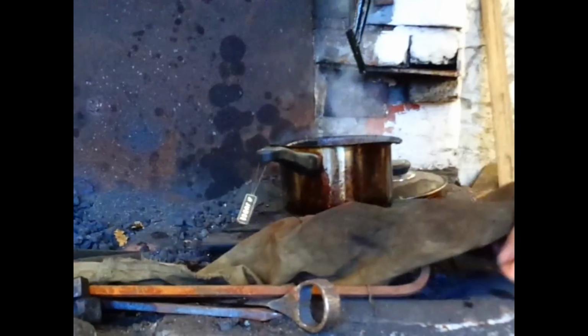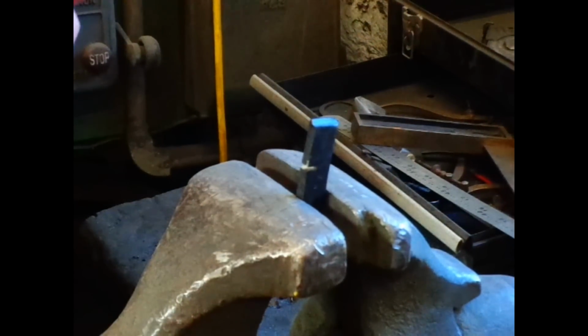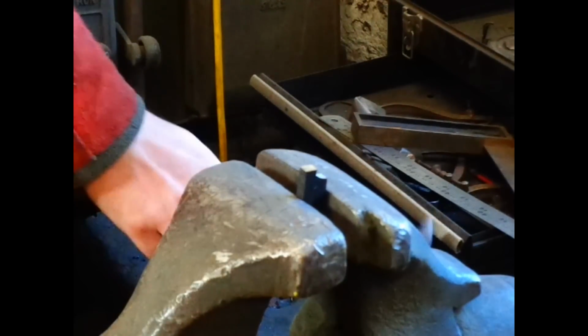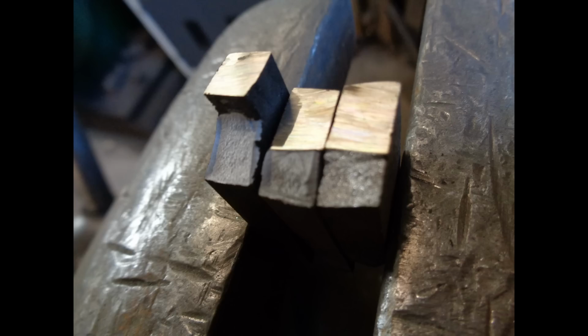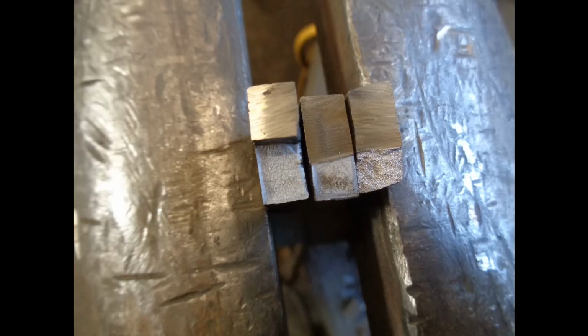I then perform the nick test. As you can see, it takes a lot more effort to snap the top off, and when it does eventually break, it's because I accidentally performed the nick test on a leftover rivet hole in the steel. Looking at the 3 samples side by side, you can see that the tempered steel is slightly coarser than the normalised sample, and a slightly different colour, while the grain boundaries are more clearly defined. The sample bounced at first rather than bending or snapping.